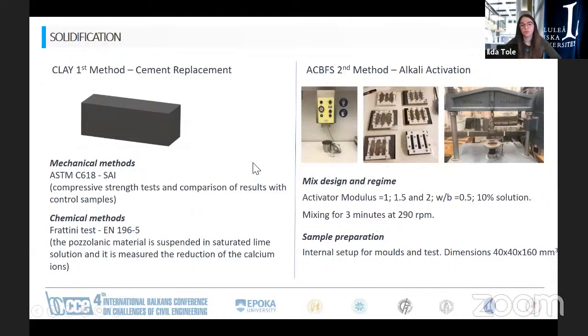Then the solidification was done with two different methods. The first is the cement replacement with clay, and the second is alkali activation. And with different standards, we evaluated the solidification rate. So 20% of the cement was substituted with clay in this case, and comparison of the compressive strength was done to evaluate whether the clay was pozzolanic or not. And in the other method of solidification, air-cooled blast furnace slag was utilized as an alkali activated material.